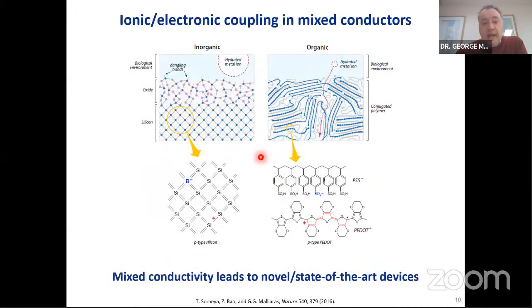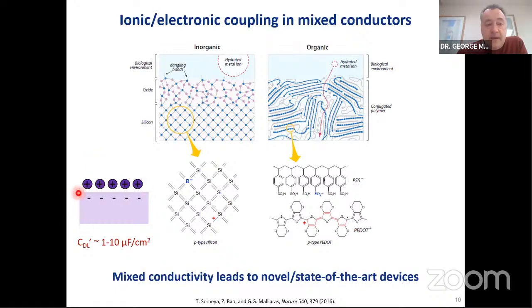The reason why the signals are weak is because what you're trying to do is to couple electronic charges in an electronic material with ionic charges in the cerebrospinal fluid. If you try to do this with silicon, you have typically an oxide or a nitride that separates your electronic material from the source of signal here. And as a result, decreases the coupling between electronics and ionics. So people use metal electrodes made out of platinum, gold, that do not have a barrier layer. And then you can have intimate coupling between the two charges, as shown here, along an interface. However, this has a limited capacitance, which measures, again, the coupling between ionics and electronics. And it's very difficult to overcome that limit.